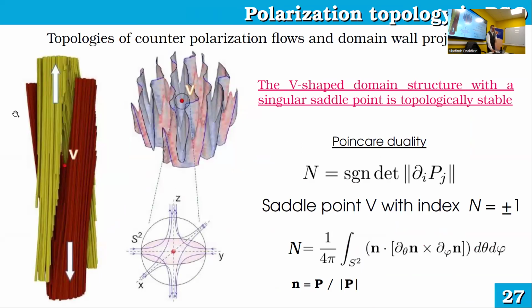So here we study some topological properties of this configuration. First of all, it's an elementary piece of this bifurcating structure. You can see two V-shaped flows of polarization, and they don't meet each other here, to avoid formation of bound charges. We plotted the surface of the domain wall in this case. It's pretty interesting that it is a singly connected surface that spans the whole volume of the crystal, and it contains a lot of V-shaped structures inside this domain wall.